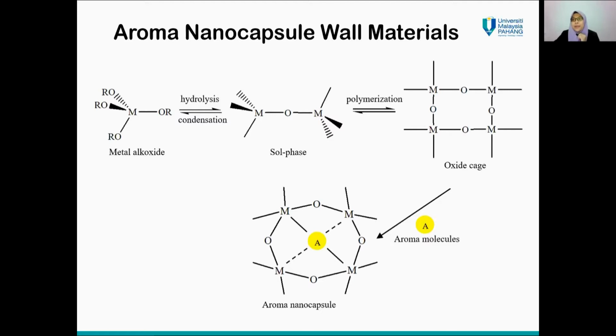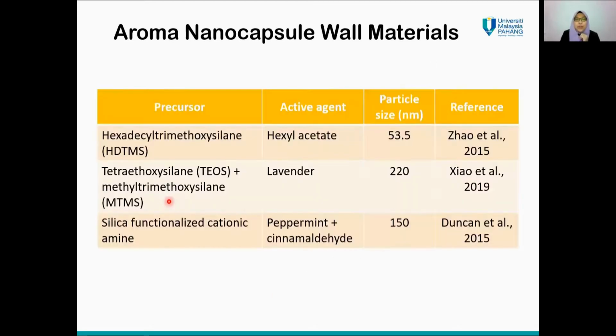So now we are going to look at the previous work done by researchers for aroma nanocapsule wall materials. First is Zhao et al. They prepared oil-to-water emulsion with the hexadecyltrimethoxysilane modified silica nanoparticles, with 53.5 nanometer size. Then these silica nanoparticles were linked with a silica precursor polymer, hyperbranched polyethoxysilane at the oil-to-water interface to enclose hexyl acetate with almost 100% efficiency.